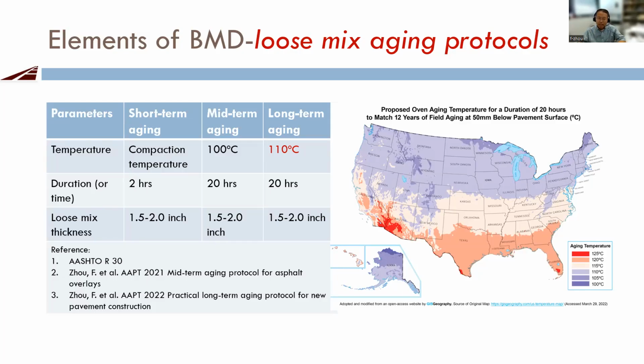For long-term aging, most of them, say in the south areas, in Texas, Louisiana, Florida, it's 120. In the middle of the area it's 110. In Oklahoma, it's 110. And above here, around 100, 105, something like that. So this simplifies the aging temperature, the time, and thickness.